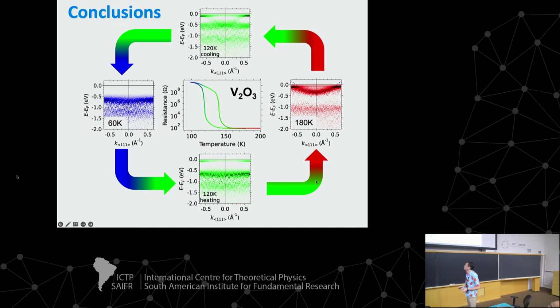Let me show my conclusions in the form of a graph. We have been able to measure how this itinerant, quasi-free electron-like parabolic state in the metallic state transfers its spectral weight to a quasi-localized state in the insulating phase with the opening of a gap that pretty much fits the gap that is known from many other spectroscopies, like optical spectroscopy, and how this electronic structure beautifully shows hysteresis as you go on a thermal cycle, cooling and warming up. Thanks a lot.